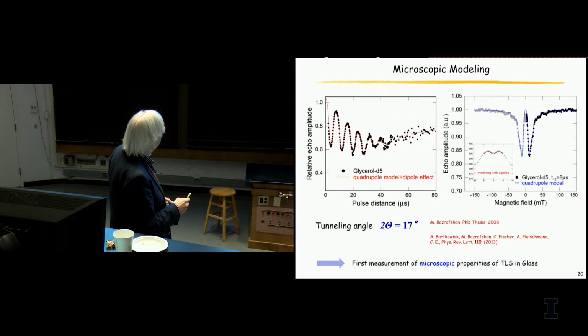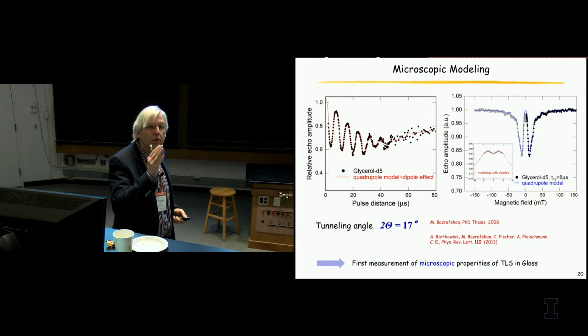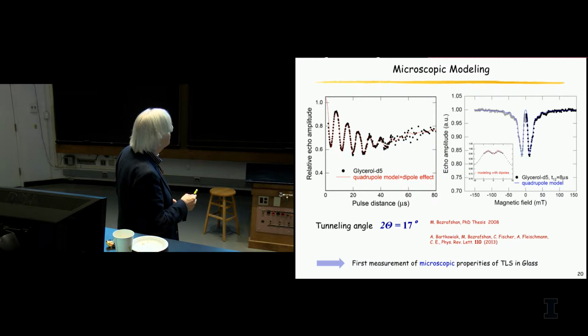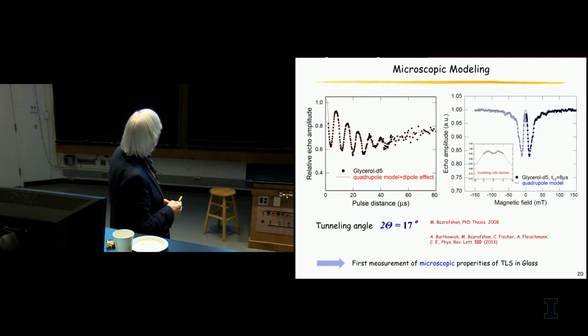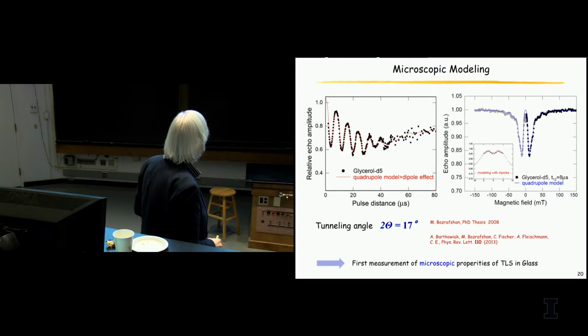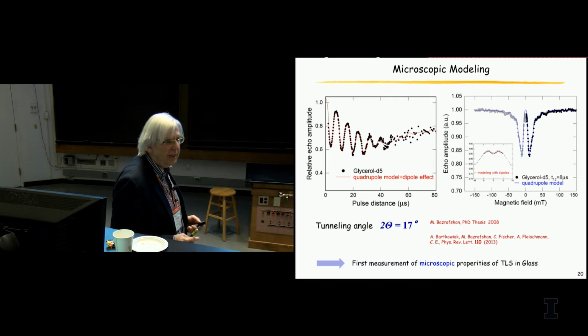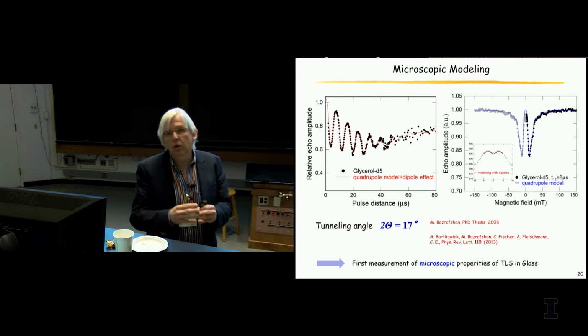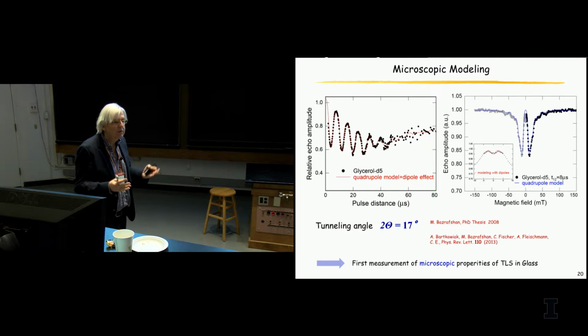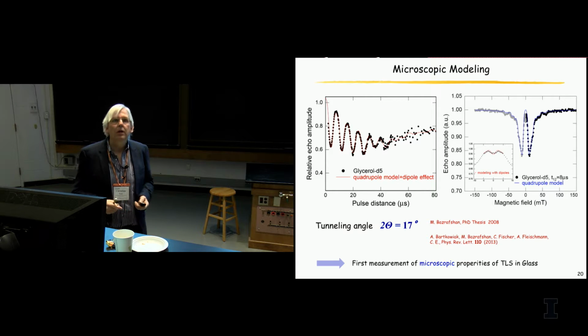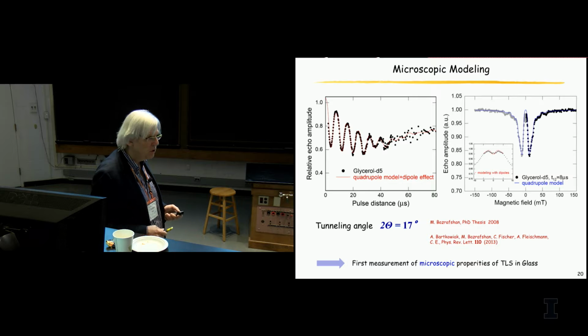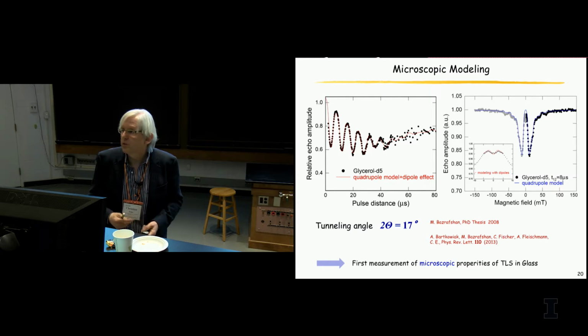There's something you had to add, which we found when we did this. There's a nuclear dipole effect. I will neglect that at the moment, but this is also happening. And when you put all this together, if you subtract the exponential decay, you see the oscillations for the quadrupole model, and then for the dipoles, this long oscillation here. So we concluded at that point that this is the first time TLSs have been really identified in a glass. This is not a typical glass, this is a molecular glass, but it is a glass, and it has also those low temperature properties which fall into this universality.